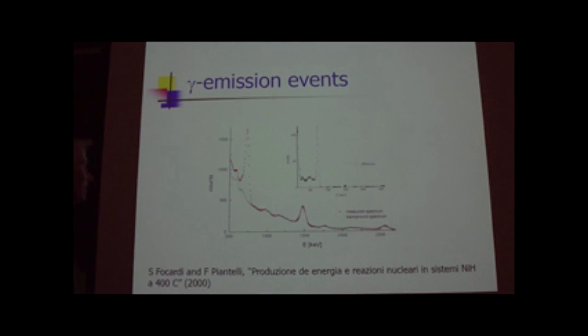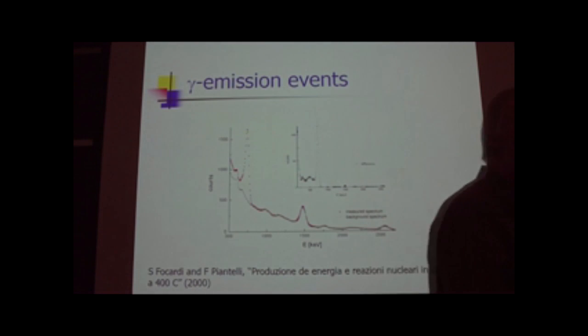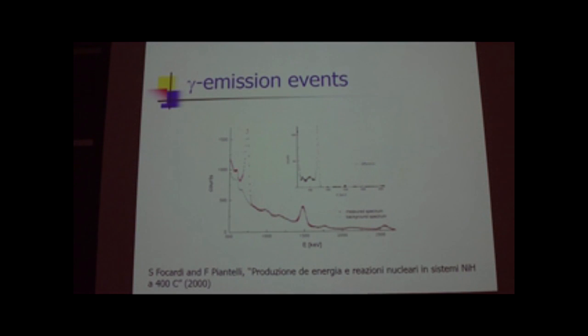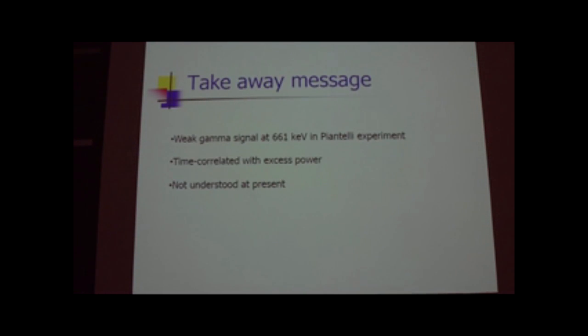In the Piantelli experiment, they reported observation of a gamma ray at a low level. This is at 661 keV, and it appears in correlation with the excess heat production at very low levels. This at the moment is not understood, but it's interesting. The level is sufficiently low that you wouldn't have to worry so much about it if you're making power and you've got one of these things running in your basement. They have a little bit of neutron production as well, that you might have to worry a little bit more about. This is not understood at present.